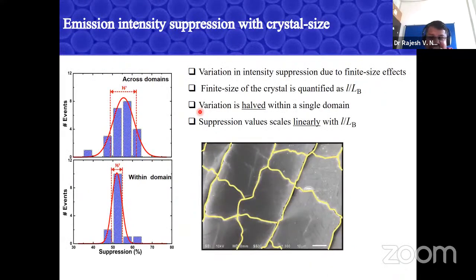So then what we did is we painstakingly took a lot of these regions. We measured the intensity spectra, or the intensity suppression, from each of these domains, and you can see that there's a huge variation in suppression across the sample. When you see a result in literature, somebody shows one intensity spectrum. Now the question is how reproducible is it? Is it the same everywhere in your sample? You can see that there's a huge variation across the domains.